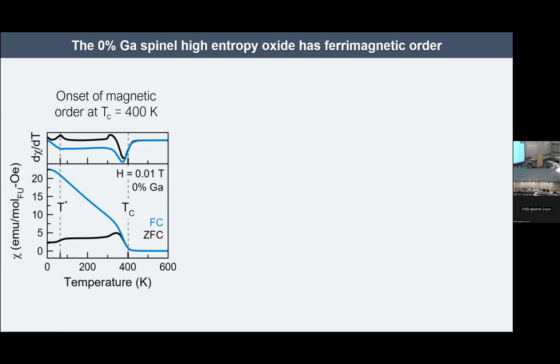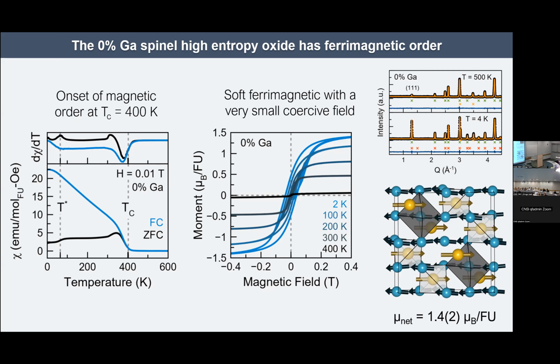Okay, so we have a ferrimagnet. Just to make sure that our assessment was correct, we performed powder neutron diffraction. And so this is how we know that there's no average structural distortion down to 2 Kelvin. It's a bit difficult to see, but this is a measurement that was collected at 500 Kelvin, and this is a 4 Kelvin measurement. You can see there's been this massive enhancement of that 111 Bragg peak, meaning that a magnetic Bragg peak has formed on top of that structural Bragg peak. So we know that the magnetic order has the same unit cell as the crystallographic order.